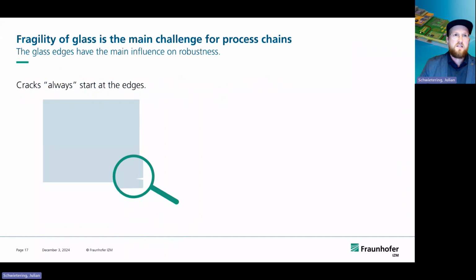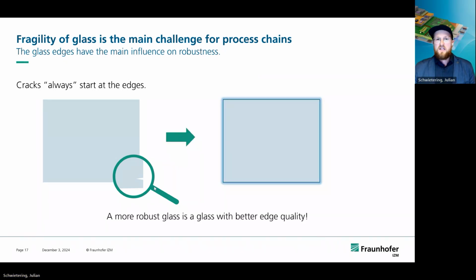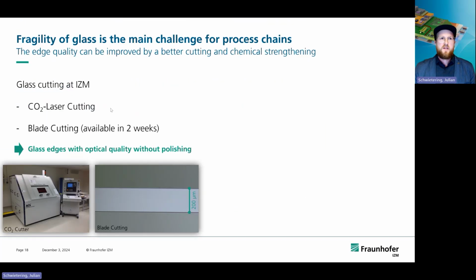The most important thing about this is that the glass edges themselves have the main influence on the robustness. Cracks nearly always start at the edges, and you have a more robust glass if you have a better edge quality. That's really important to know, and that's why we are focusing on the cutting of the glass. We are using a CO2 laser, or in future, we will also use a blade to cut the glass, to have good quality edges, and also optical quality of the edges to connect optical fibers.